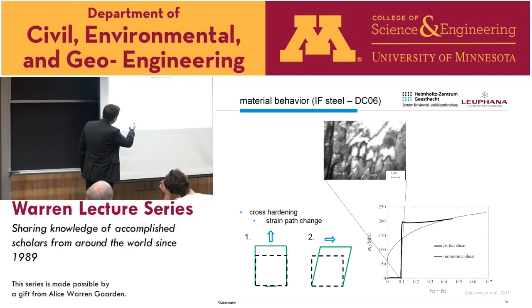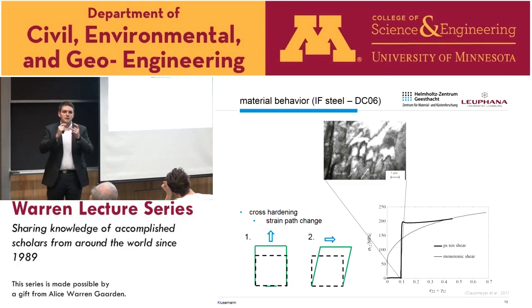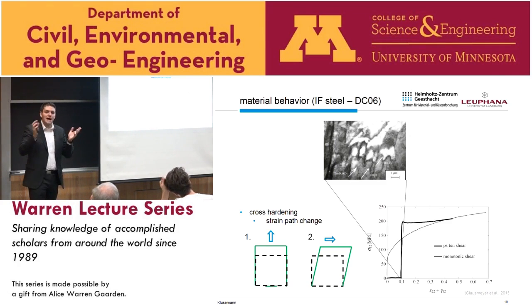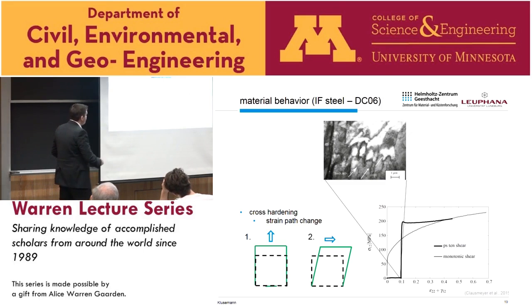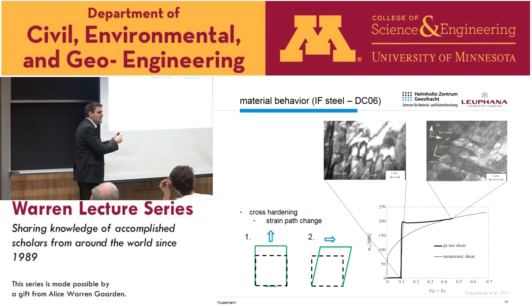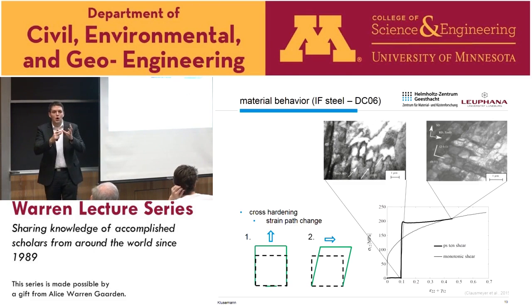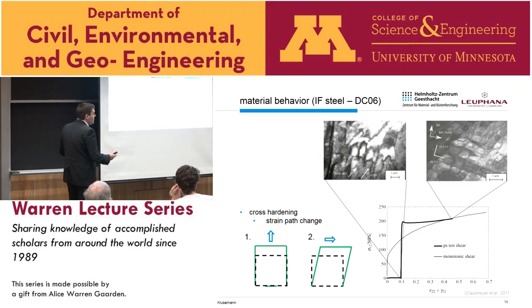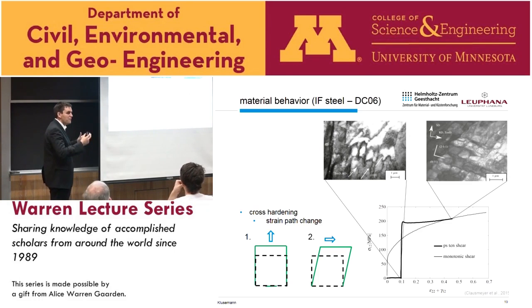Well, we investigated the microstructure, and what you can see is, this is the loading direction, and orthogonal to this you have very strong and thick dislocation walls. So it's a kind of latent hardening behavior, if you want. And when I now change the loading direction orthogonal to that, of course these dislocation walls have to be overcome. So they have to be rearranged, destroyed, however you want to name it. And in this regard, you get a complete reorientation or reorganization of your dislocation microstructure, and then of course it also fits the monotonic shear stress-strain response.